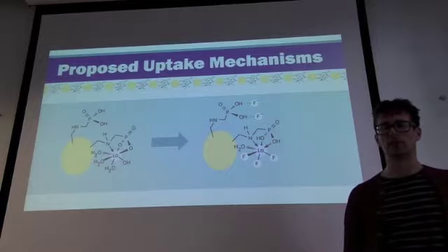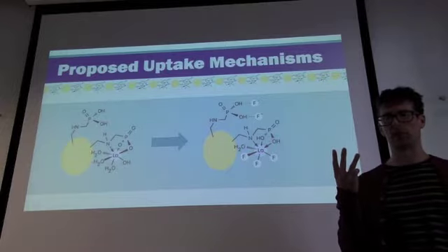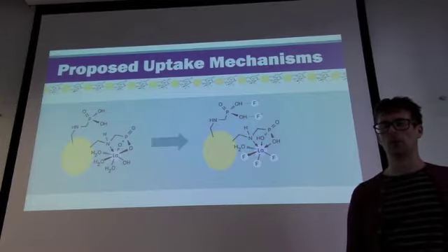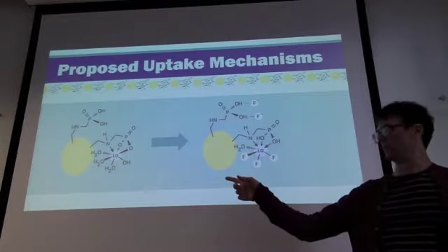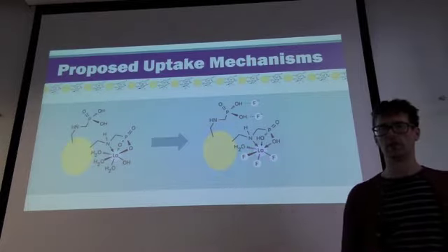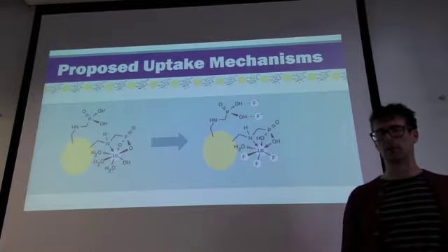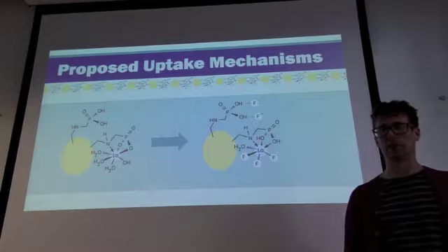We can then start to try and translate that to what's going on at an atomic level. It turns out there are actually 3 different uptake processes to consider here. The first 2 are very fast. One is the direct exchange of water and hydroxyl ligands for fluorides. There's also this secondary hydrogen bonding interaction between the aqueous fluoride ions and the unoccupied aminophosphonic acid coordination sites that do not have a lanthanum ion on them.